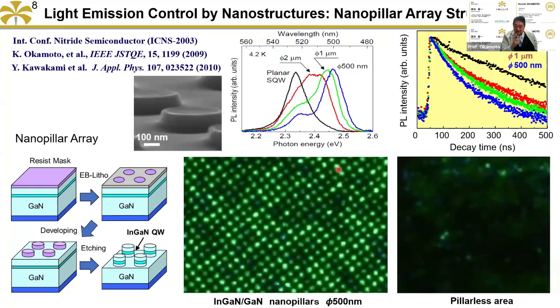Also, an important thing is that you can control the light intensity, the spectrum, and also the emission lifetime. With decreasing structure size, the lifetime becomes shorter and shorter. So that's important, that you can control the spontaneous emission rate. And another important thing is that you can see it's moving. You can see the blinking feature.